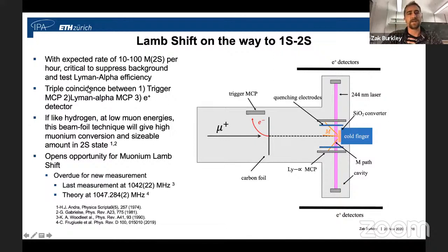So for the MuMass experiment, what we need to count as a signal is we need to trigger that we have a muon coming through our carbon foil. So here's our signal number 1, that we have a muon. And when we get this trigger, it says, hey, you should look a microsecond or 2 later for any metastable muonium. You should be looking for Lyman alpha light. And then 2, we see this Lyman alpha light. And then 3, we see the decay of the muon through a detection of a positron. And that's our triple coincidence to eliminate any background and be sure that we saw an event.